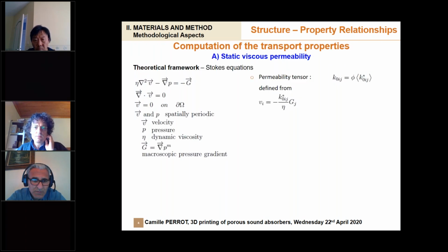So let's go back, but very briefly, to the basic equations governing the permeability, which is an important parameter governing the sound absorption behavior of porous material. Basically, you have to solve the Stokes equations, which govern the asymptotically low frequency behavior of your porous material. By field averaging of the velocity field, which is a solution of this Stokes problem, you can get a rescaled parameter, which is a permeability field. And when you average this permeability field through your phase field, you get the permeability tensor, which means that you can compute it in at least 3 different orthogonal directions.